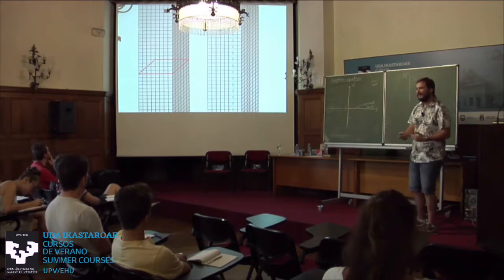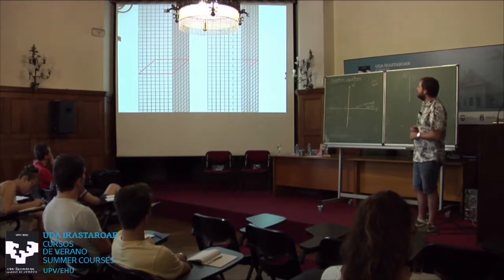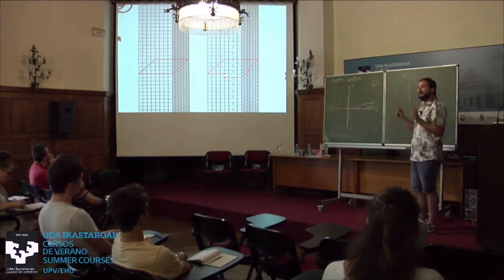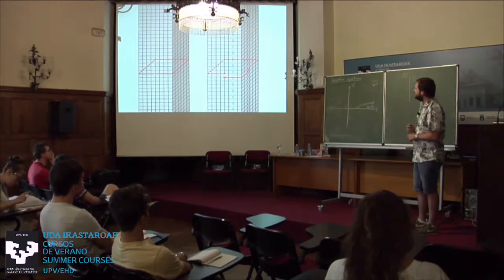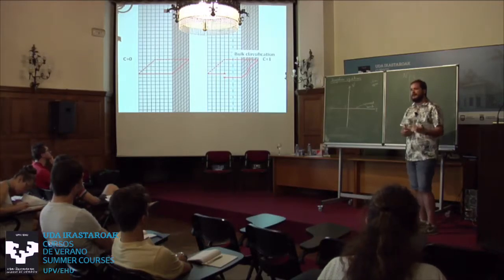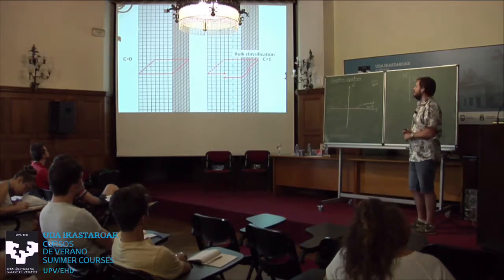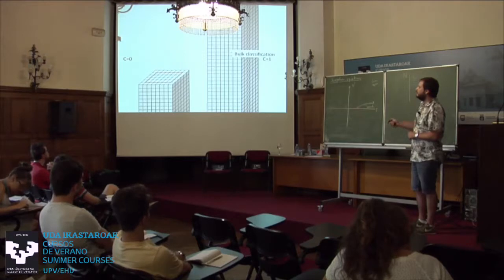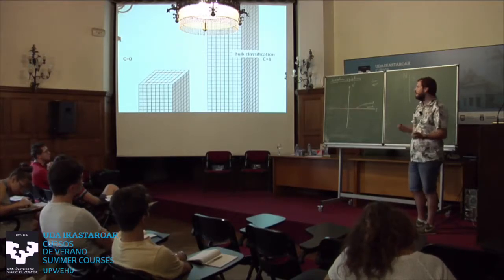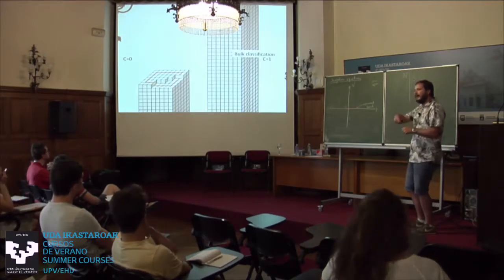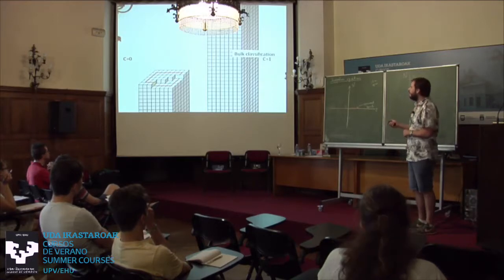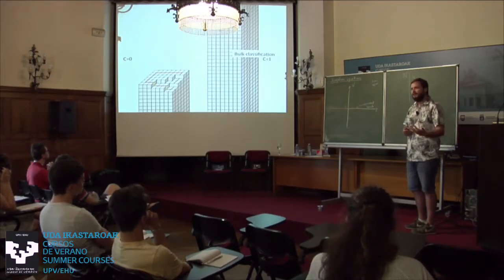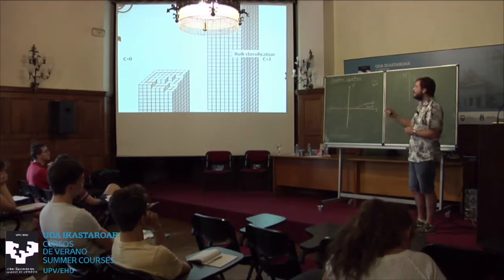If I draw the contour in a crystal that has a screw dislocation, I get a one unit cell displacement — this is the Burgers vector, the topological index that classifies the screw dislocation. So there is a bulk topological classification of crystals in real space. Now introducing a surface termination: in the trivial case, drawing a closed contour on the surface always crosses an even number of step edges — there is no way to get an odd number.